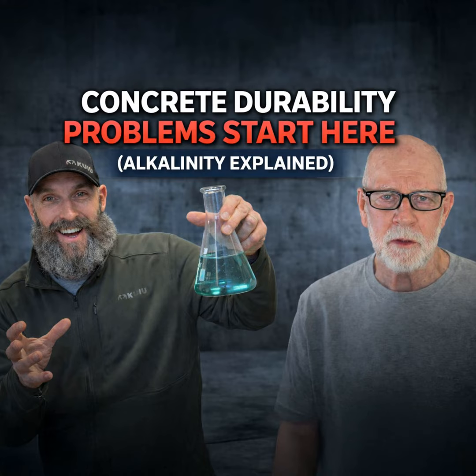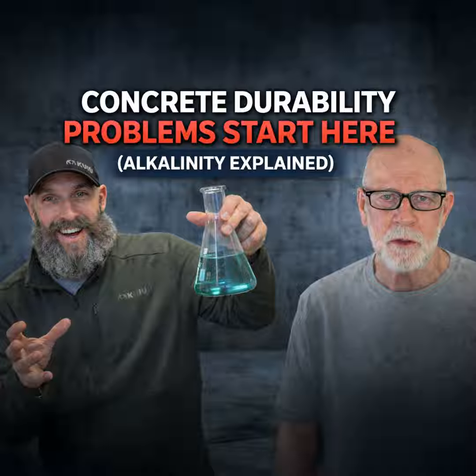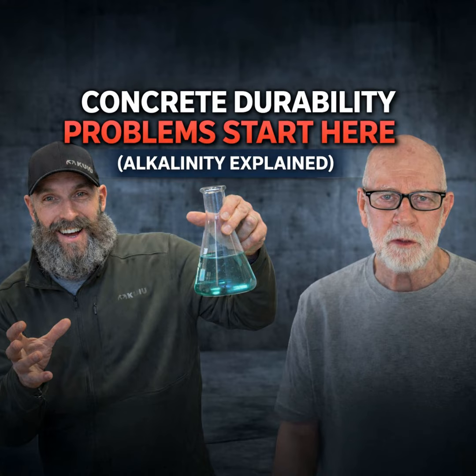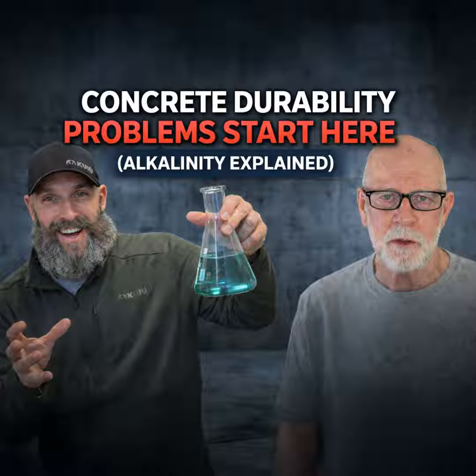And here's why. One famous consultant said, well, the reason why calcium chloride isn't accurate is because it overdries the concrete. Well, that's nonsense, because it has what's called a higher critical humidity threshold. The calcium chloride has a higher humidity threshold than the alkaline salts. The calcium chloride in these test devices will try to get the relative humidity down to 18%. That's its critical humidity threshold. It'll start attracting water and will hold on to water at 18%. So if the relative humidity is higher in these air spaces, it's trying to get it back down to 18%. And that's how calcium chloride is used in closets.